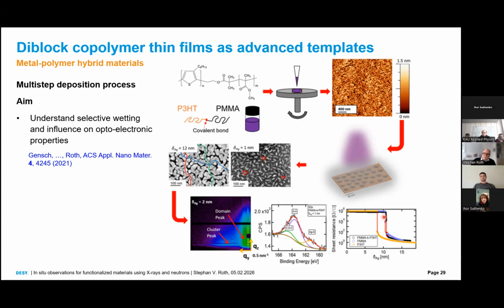Neutrons we use more for our biomaterials when we look into polymers. There are different polymers like cellulose and PEDOT:PSS, where we look into the different structures of these polymers, for example, during humidification. Then we know that we can measure for 3 hours per sample without any problem. So with neutrons, you are completely right. We are typically limited to the minute to hour range. I think the record for GISAXS is 60 seconds or 10 seconds, something like this, but much longer. So really GISAXS with a two-dimensional image.